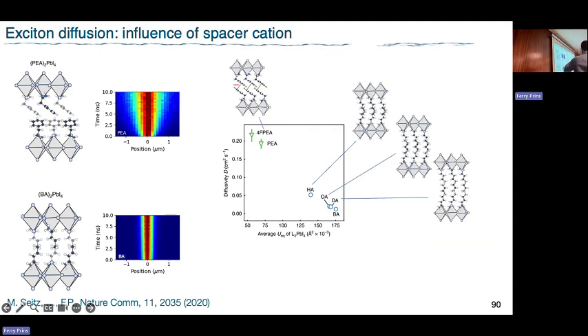The slightly more elaborate story here is that in perovskites we're not really dealing with just an exciton, but the presence of the exciton deforms the lattice, so it's actually a polaron. What you're moving is not the exciton in the lattice, but a deformation of the lattice, which is why this is so dramatic. You slow it really down because the polaron becomes much more dominant here than it is in a rigid lattice.